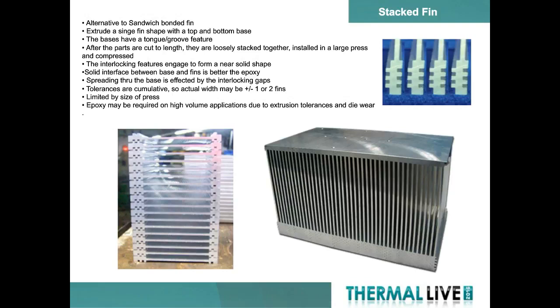One downside is because each fin is extruded and has its own tolerance, the tolerance on the overall width of the part is cumulative. So if you want a 9-inch extrusion and 15 fins, you might actually end up with a 9-inch wide extrusion that has 14 fins if all of the fins come in slightly oversized.